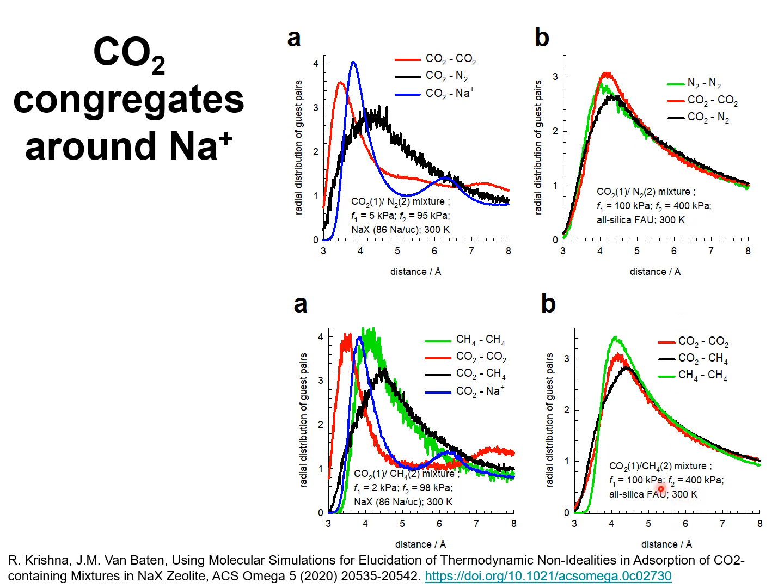An identical situation holds for CO2 methane mixture adsorption in all silica Faujasite. The distances between any of the pairs, CO2 pair or CO2 methane pair or methane pair, is practically the same.